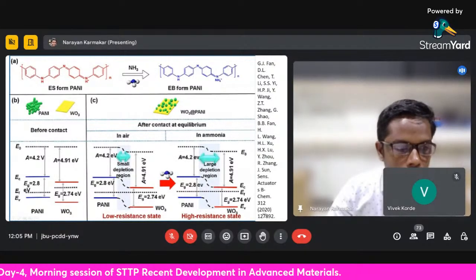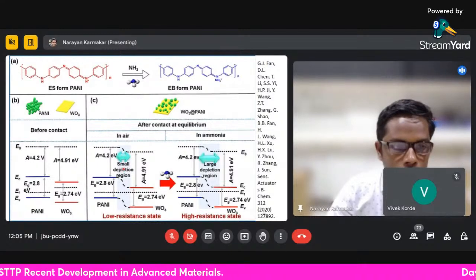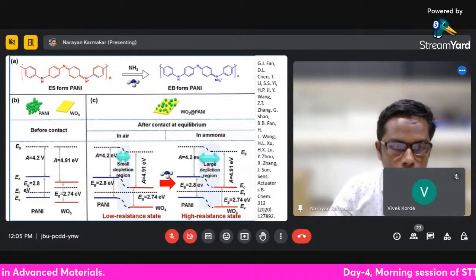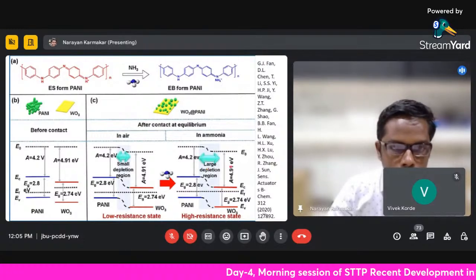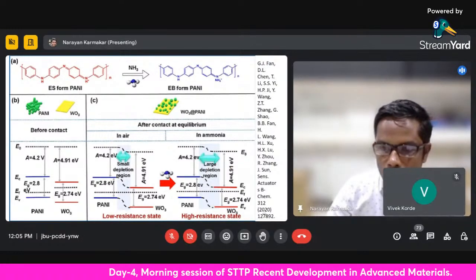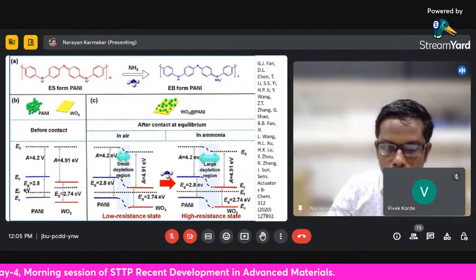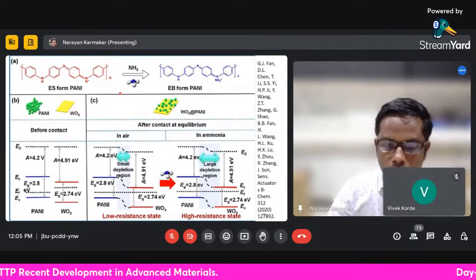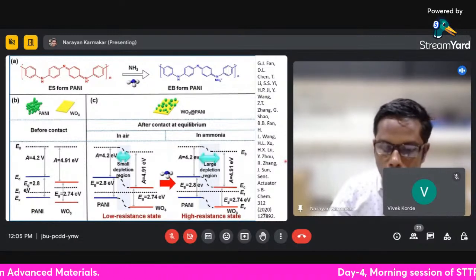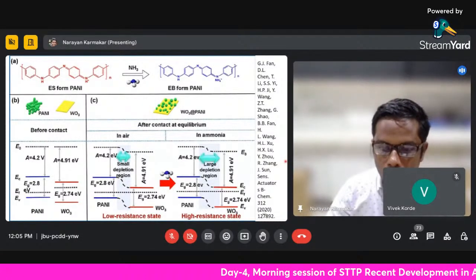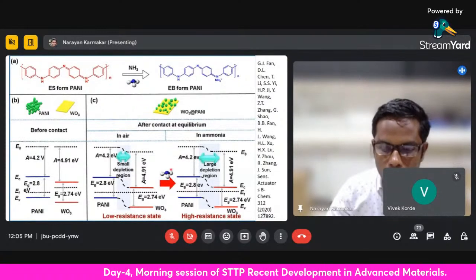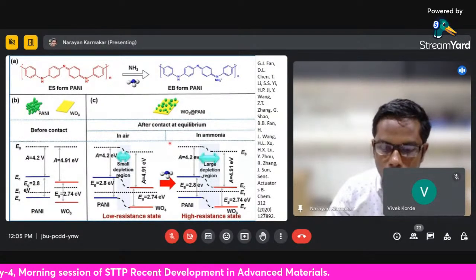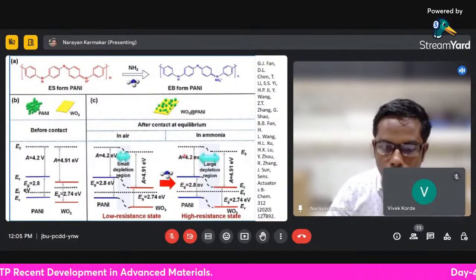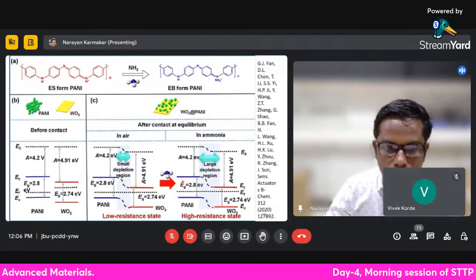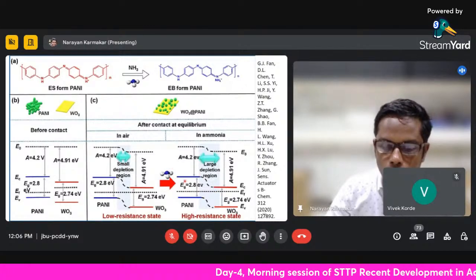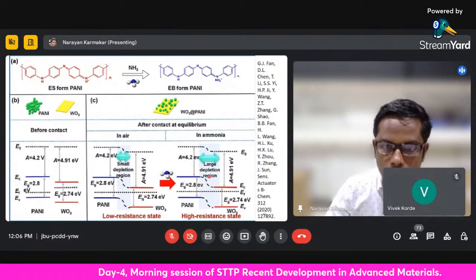So we can see that in the presence of air, the depletion region is narrower, but in the presence of ammonia, it is wider. Because what is happening here? Look at this reaction. This is happening because the adsorbed ammonia molecules consume holes and protons from the amine groups of Pani, which results in the conversion of the emeraldine salt to emeraldine base. Because of this process, the widening of the charge depletion region is happening, and hence the potential barrier of this tungsten trioxide-Pani interface increases, and because of that, the resistance is increasing in this case.